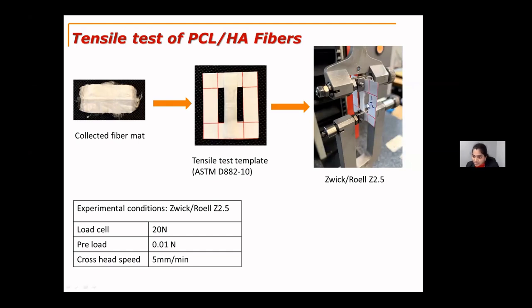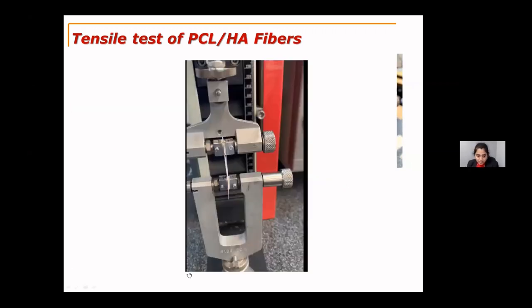And this template is loaded here, and we cut this template so that the force from this paper will be removed. And this is loaded in this machine, and we perform the tensile testing on these nanofibrous mats. I did 10 samples for each case, and I took the 5 best out of them and averaged the results. For each test, it took almost 40 minutes. So I made a short video for the tensile testing.